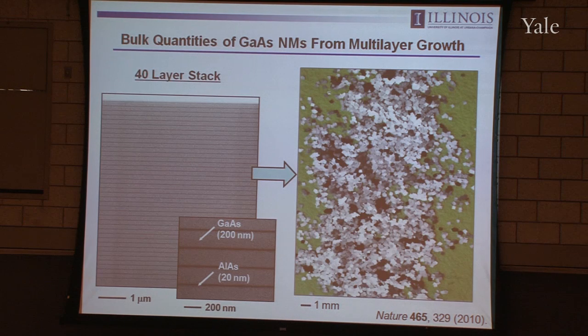This works extremely well. Here's an example of a 40-layer stack where we have 200 nanometer thick sheets of gallium arsenide separated by 20 nanometer thick layers of aluminum arsenide, etched down through that stack, immerse it in this hydrofluoric acid. That eliminates the aluminum arsenide. Off pops a lot of these gallium arsenide membranes into the solution bath, and then you can deposit them down onto another surface. You create bulk quantities of these kind of nanomembrane form semiconductor materials. And so each one of these little squares of gallium arsenide can serve as an active material component of a wide range of devices in electronics and other kinds of systems.